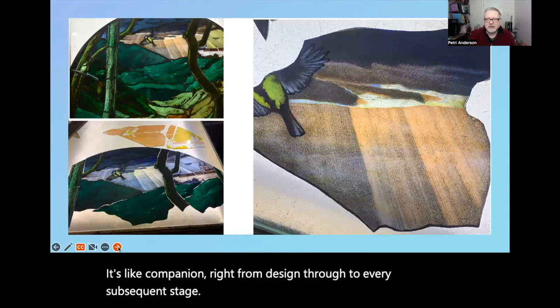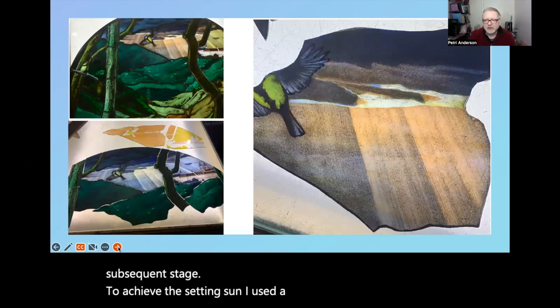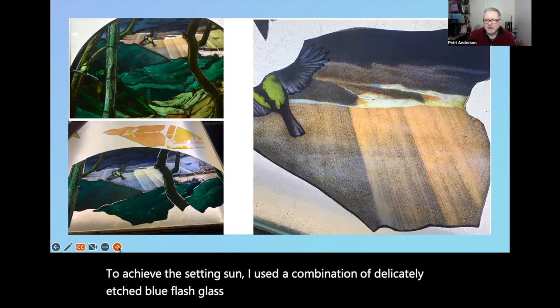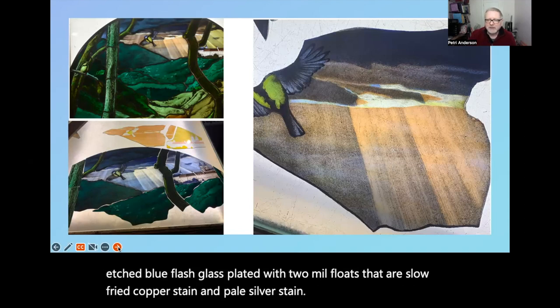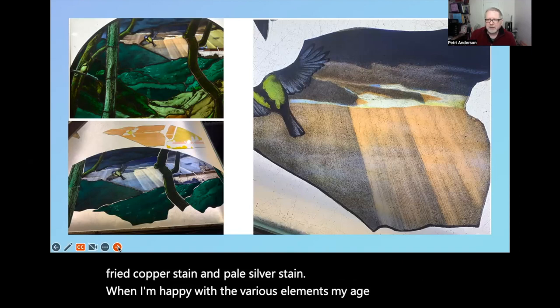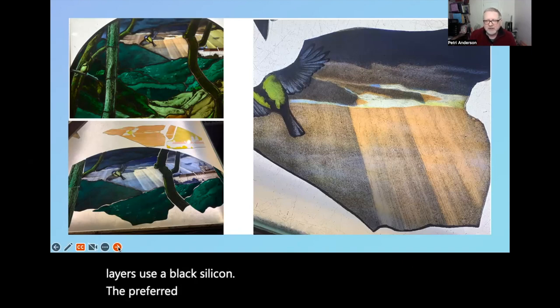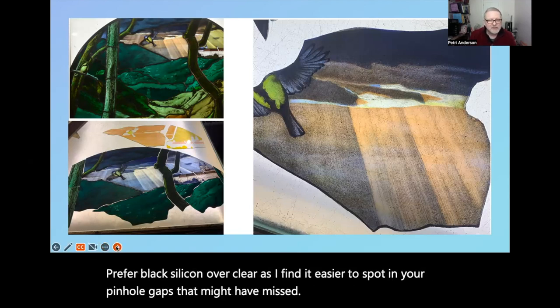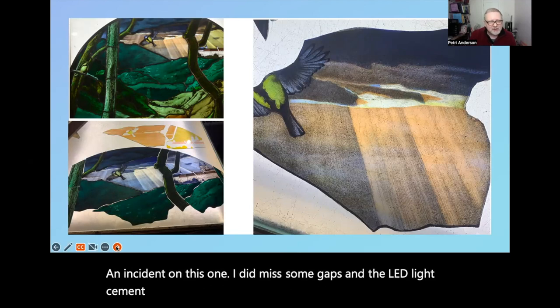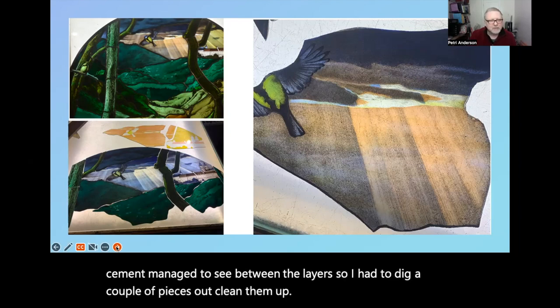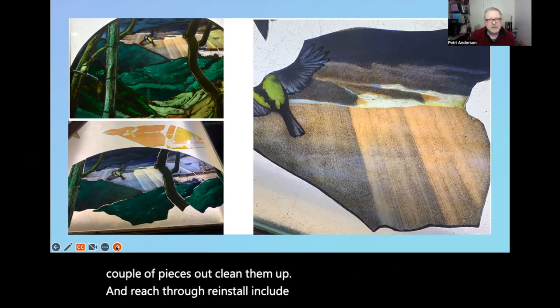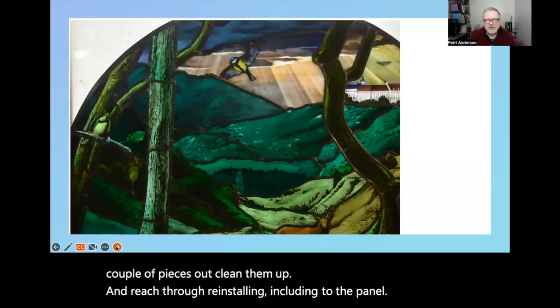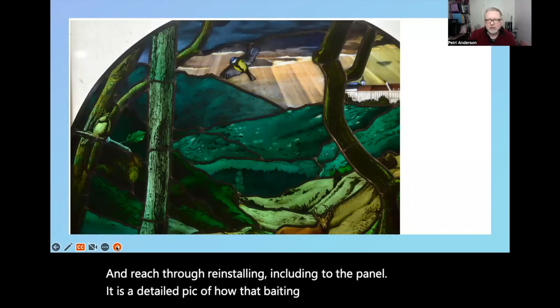To achieve the setting sun, I used a combination of delicately etched blue flash glass plated with 2mm float that is low-fired copper stain and pale silver stain. When I'm happy with the various elements, I edge bond the two layers using black silicone. I prefer black silicone over clear as I find it easier to spot any pinhole gaps that I might have missed. And incidentally, on this one, I did miss some gaps, and the lead light cement managed to seep between the layers, so I had to dig a couple of pieces out, clean them up, and reinstall them into the panel. And here's the detailed picture of how that plating works in the broader context of the rest of the panel.